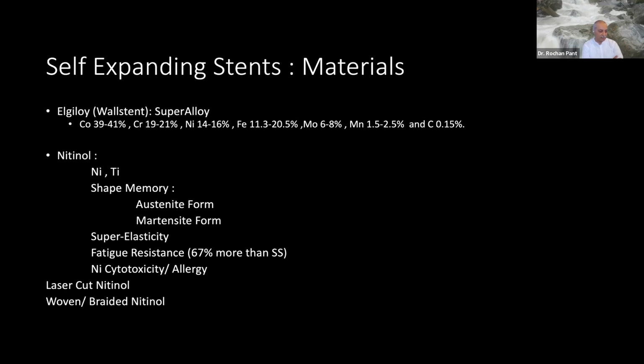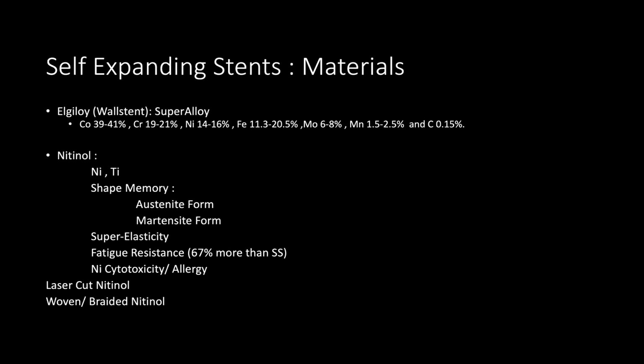Almost all the other stents are made of nickel titanium. It's a shape memory metal, which means it has two forms, and the transformation occurs at a certain temperature. It's called a critical temperature: the austenite form and the martensite form. And in nickel titanium, the transition point is near body temperature. So it's a super elastic metal, has shape memory, so it expands to attain its size. So you can create it at a particular size, then restrain it into a smaller profile for inserting into the body for deployment. It's usually deployed by pulling back the covering sheath.